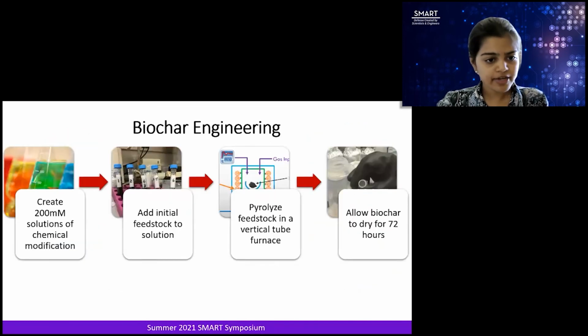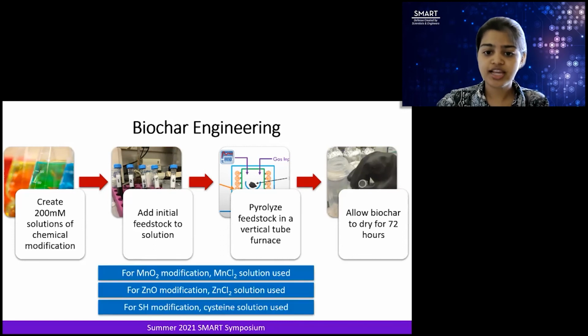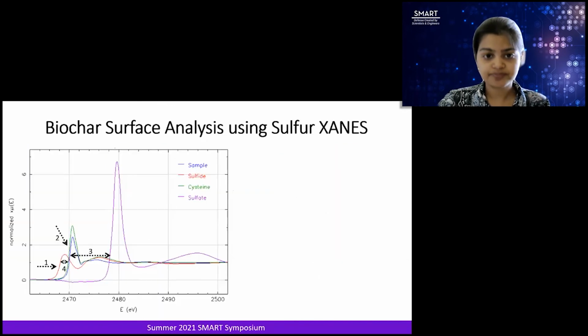To engineer my biochar, I first created 200 millimolar solutions of chemical modifications, then added the initial feedstock, so either rice husk or oak wood, to the solution, and then pyrolyzed it in a vertical tube furnace. I then allowed the biochar to dry for 72 hours. For manganese oxide modification, I used manganese chloride. For zinc oxide modification, I used zinc chloride, and for a thiol modification, I used cysteine.